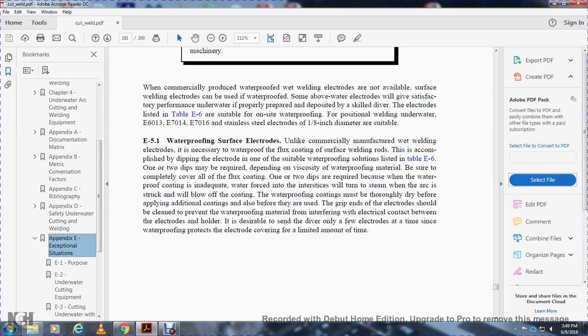E5, waterproofing surface electrodes. Unlike commercially manufactured wet welding electrodes, which have a waterproof flux coating, surface welding electrodes must be waterproofed by dipping the electrode in one of the suitable waterproofing solutions in table E6. One or two dips may be required, depending on the viscosity of the waterproofing material. Be sure to completely cover the flux coating. Water trapped in the interstices will turn to steam when the arc is struck and will blow off the coating. The coatings must be thoroughly dry before applying additional coats.